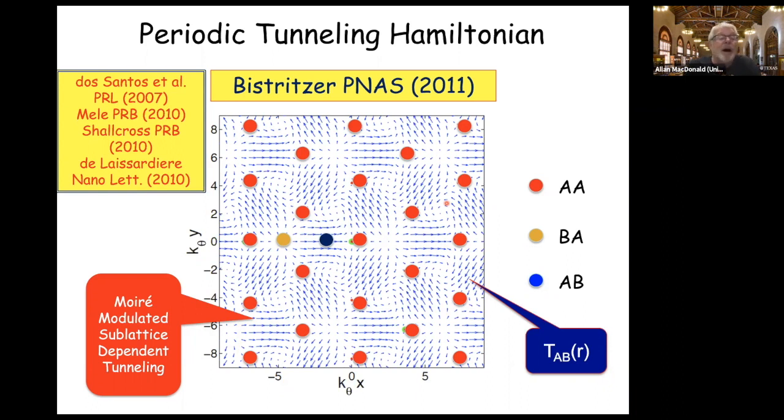So the model that describes twisted bilayer graphene is a model with two graphene sheets with linearly crossing bands and tunneling between the layers that's position dependent, that varies slowly in space on the scale of the Moire pattern. For example, at some points where the stacking is AB or BA, the electronic structure is just the one I showed you a moment ago.